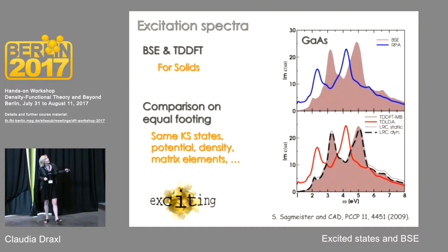The problem here is that the random phase approximation has not been computed from GW, but from DFT. That's why the gap is underestimated. But if you do a GW calculation or apply a shift, then you end up with this spectrum. Now, alternatively, you can use time-dependent DFT. You see TD-LDA, again, is underestimating the gap. And I shifted it on purpose, because for molecules, TD-LDA gives you both. It opens the gap and brings the spectra back due to electron-hole correlation.